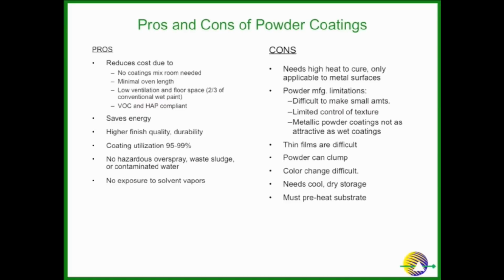Usually when people actually run these lines, it's closer to 70. But you can get very high utilization. Right? The overspray is gone, no solvent vapors. It's good for the environment, good for protecting people's health. It's difficult to make small amounts of powder. So you have to make this powder in big batches for it to be economic. All right? It's not technically hard, it's economically hard. So you can't get small batches when you need it.